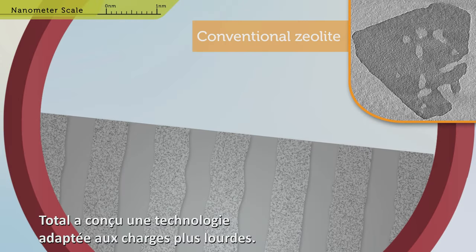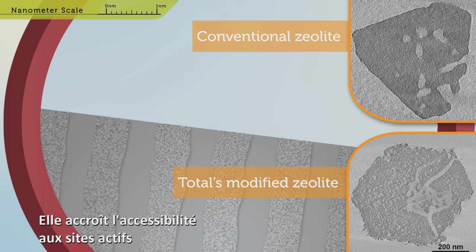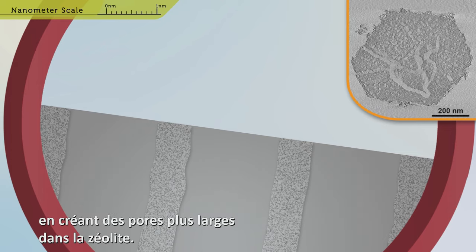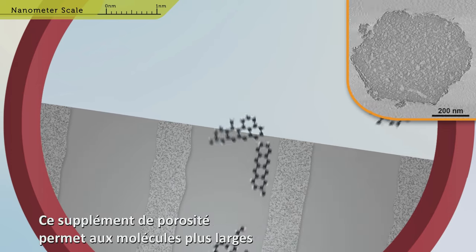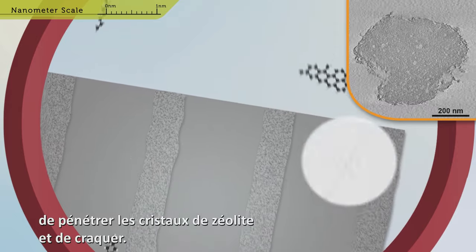At Total, we've developed a technology tailored towards heavier feeds. The technology provides increased accessibility to the active sites by generating larger pores within the zeolite. The extra porosity allows the larger molecules to enter the zeolite crystals and crack.